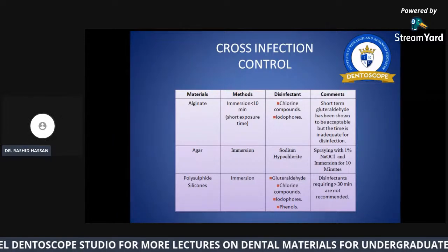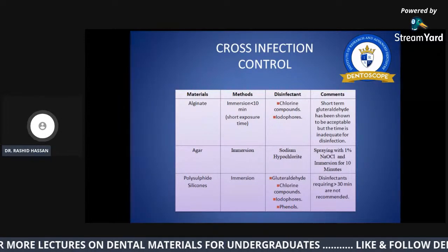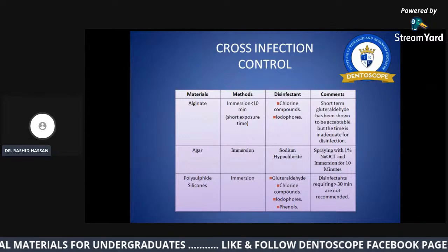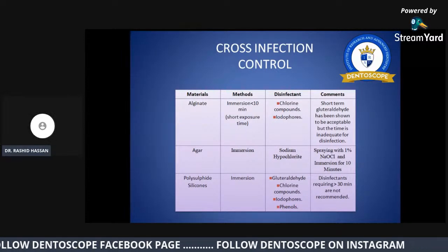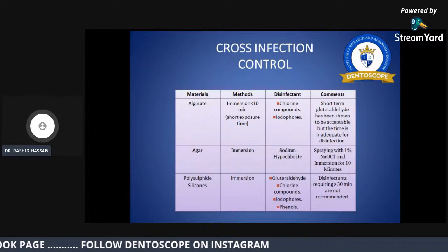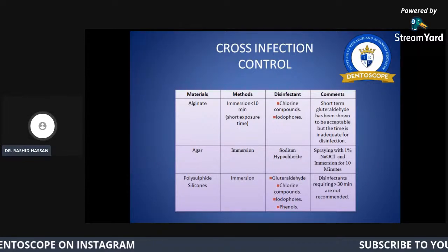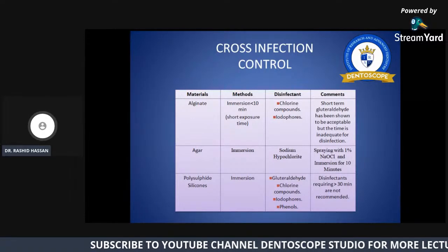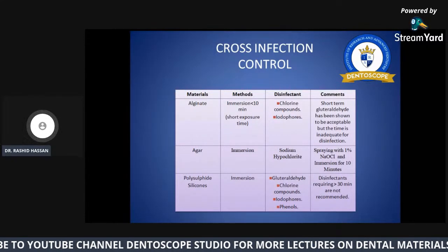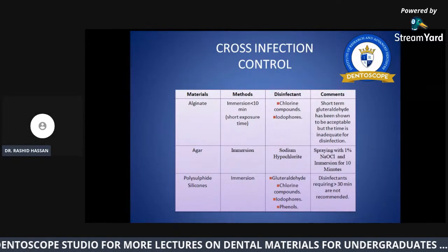So you immerse it for 10 minutes either in a chlorine compound or the iodophore, and you get the alginate impression material disinfected. In the comments here, it is mentioned that short-term glutaraldehyde has been shown to be acceptable, but the time is not adequate for the disinfection.